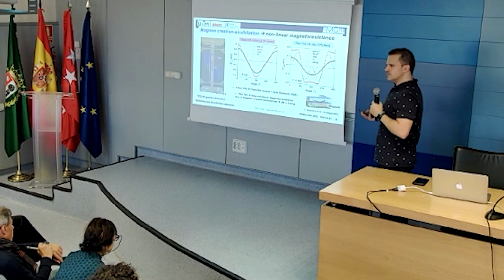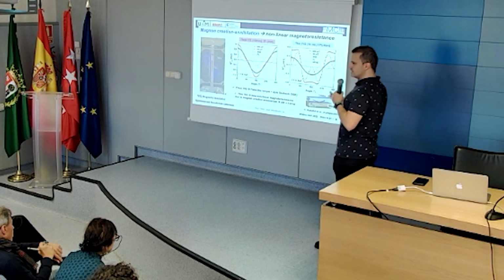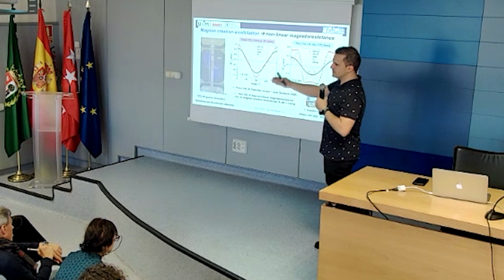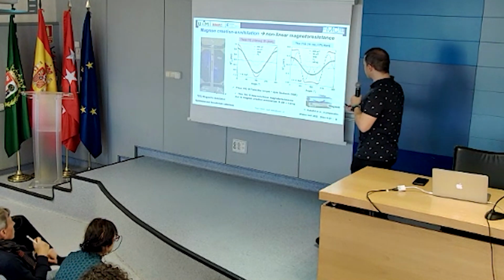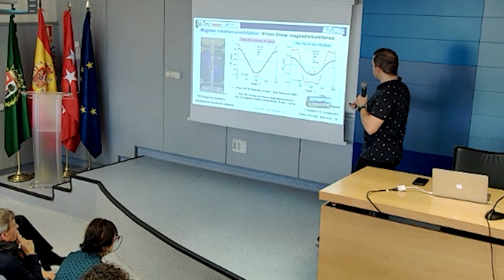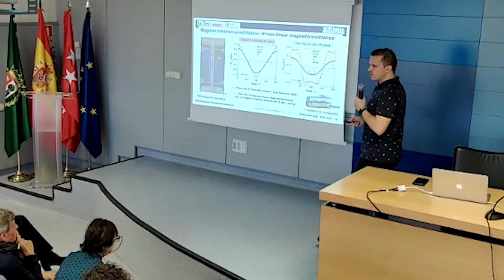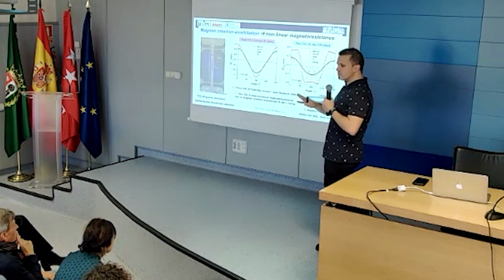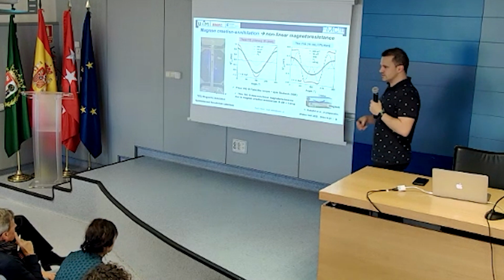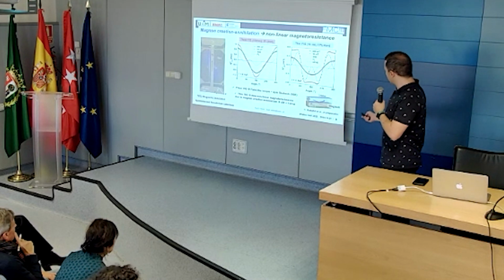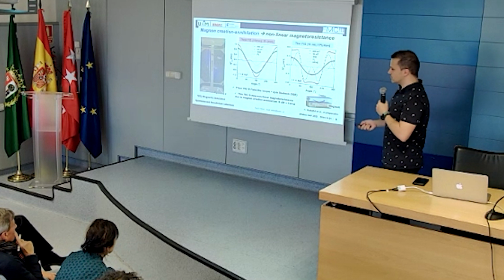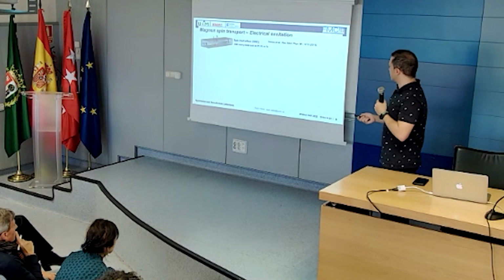So what we interpret is that we are compensating the damping in the system because we are pumping spins into the system. And basically we have this additional angular dependence that leads to a new magnetoresistance effect, that relates to this spin-flip scattering because of the creation of magnons. Let me connect to what magnons are.